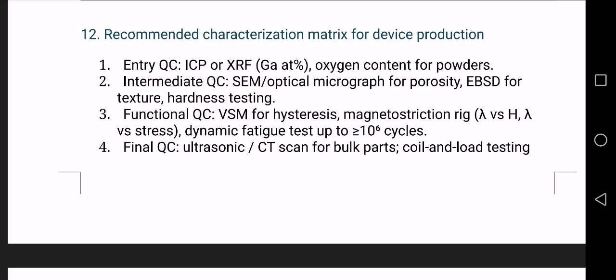Next we have mechanical screening. Hardness testing detects over ordering, excessive brittleness, improper heat treatment quality. Functional quality control is done using VSM, hysteresis loops, coercivity, saturation magnetization, and magnetostriction testing, the critical tests: lambda versus applied field.